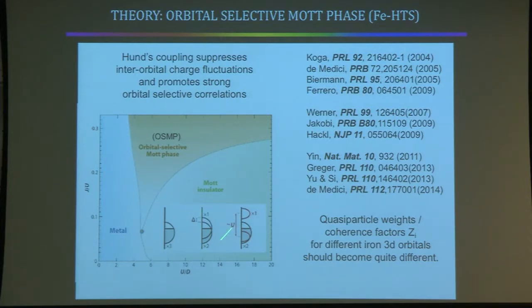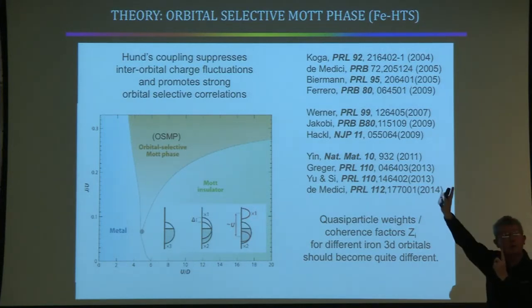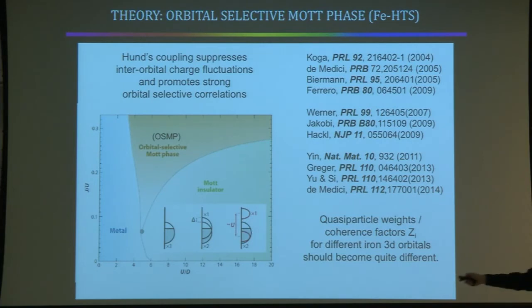Now, one thing that motivates this very strongly is Hund's coupling. If you have an atom with Hund's coupling between 2 orbitals, what the Hund's coupling does is it aligns the spins in the 2 orbitals, but it suppresses the charge fluctuations between them. These are 2 orbitals on the same atom which stop communicating because of the Hund's coupling. Once the charge fluctuations are suppressed, then each orbital can have a different fate in forming the band structure. One of them could become localized, and the other one could become delocalized.